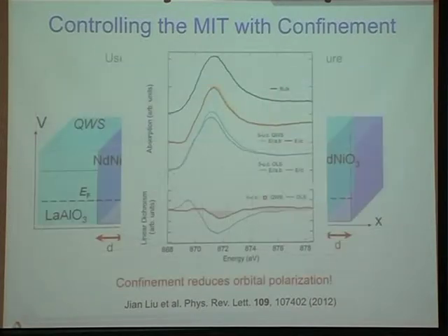And it turns out that the big difference here is that when I have just a single layer film, I have a lot of orbital polarization. But when I put that thing into a heterostructure, especially if the layers are thin, that chemical pressure effect that I showed you in the previous example comes into play. And actually, if I'm under compressive strain, these two things are working against each other. So what happens is, in a quantum well, I can take a material like this at a single layer, which has an orbital polarization, and put it into a quantum well, and I can completely kill out that orbital polarization. And it seems like this is very closely connected to whether or not one can bring back this metal-insulator transition.